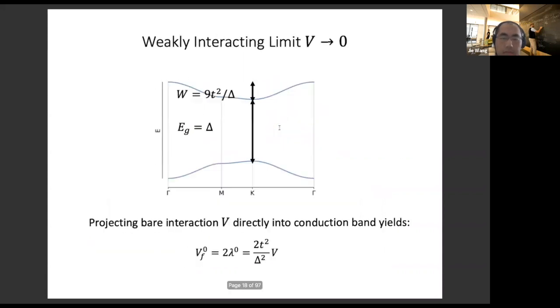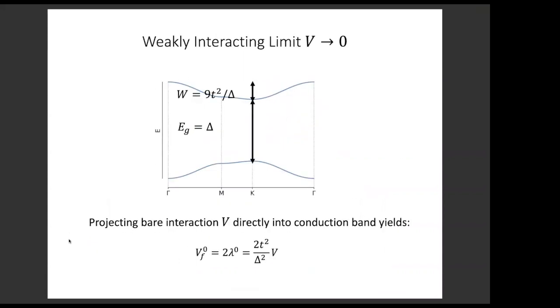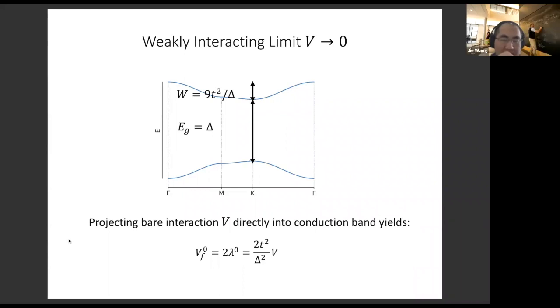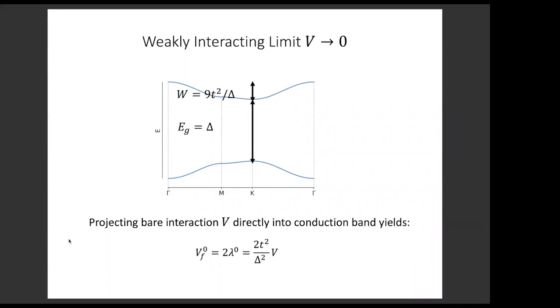Next slide. Okay. And indeed, we can actually look at the small V limit. In a small V limit, the natural way to think about it is to first think about the formation of bands due to the hopping T, and then we project the interaction into this narrow band. In that case, the Wannier function in the conduction band is mostly on B side, but it has a small mixture with the A side. And the interaction V is between nearest neighbor A, B sides. Therefore, once you project the interaction into this conduction band, you find a much smaller effective repulsion between doped electrons, which is proportional to T squared over delta squared. But you also find correlated hopping. So correlated hopping emerges very naturally, okay?